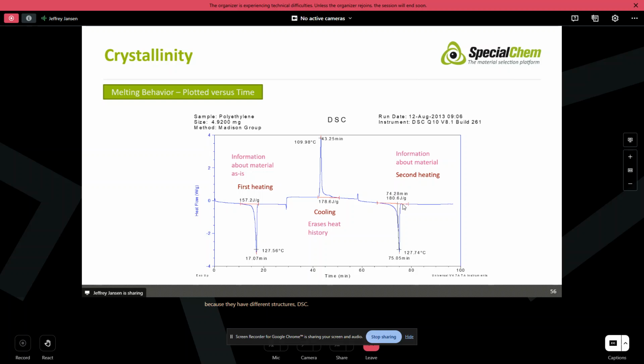So we talked about how important crystallinity is, and it can be very, very important in performance properties of materials. Okay, we want to understand how crystallinity impacts performance. So higher levels of crystallinity are going to give us, in our molded part, better creep resistance. They tend to give us better fatigue resistance, higher tensile strength, stiffer materials. So in many cases, again, we're trying to optimize the crystalline structure of the material through the molding process. Well, DSC is going to help us evaluate that. So for that, we're going to run what's called a heat, cool, heat run. And I've got it again plotted in time. We don't normally plot this in time, but I wanted you to understand how this works.